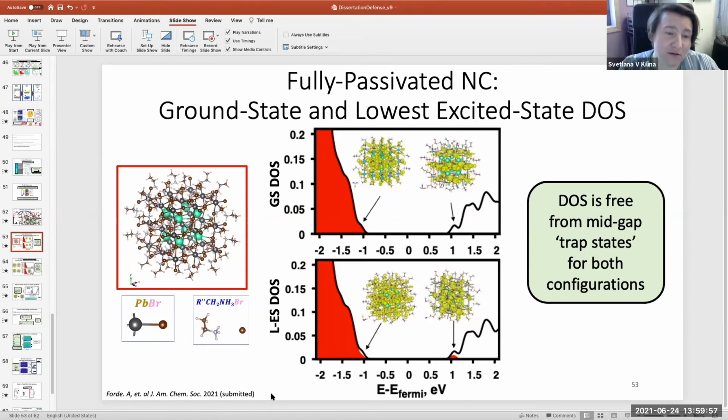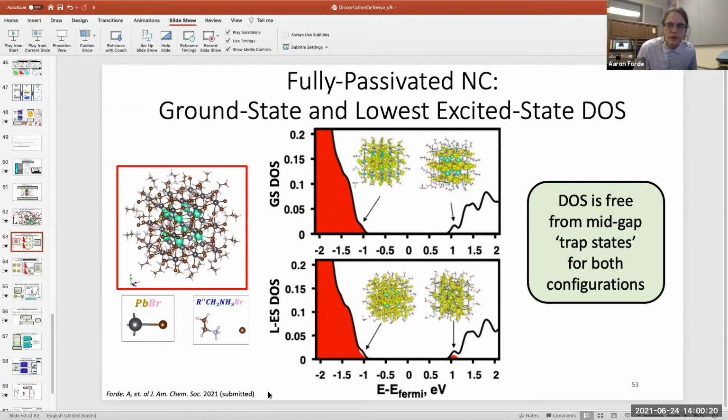And do you have any evidence with direct experimental comparison, let's say absorption spectra or something, which will justify this approach? Yeah, so the comparison would be to compare the spectra we compute to something higher level, like TD-DFT or Bethe-Salpeter. It hasn't been done for the models in question, but in a more general framework, in the strong confinement regime for the nanoparticle, the Bohr radius is like 8 nanometers, and here it's 2 nanometers. So you have contributions from 1 over r squared and 1 over r, and the 1 over r squared is more dominant than the Coulomb.